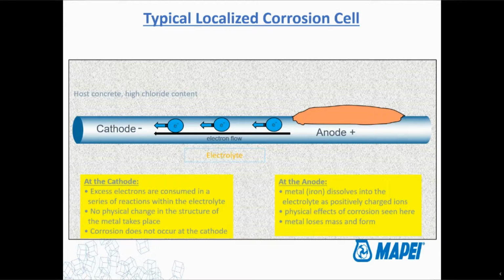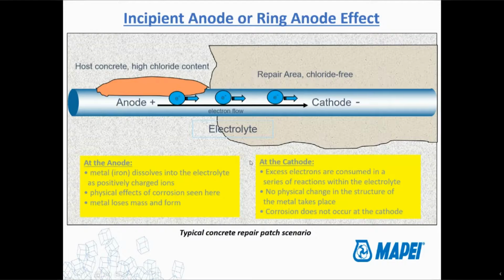It's very low potential. There's not going to be corrosion happening in that area because the steel is going to repassivate from the high pH. The low chloride concentration will also help repassivation of the steel. But you're going to have all that happening immediately adjacent to really high potential concrete on all four sides of it that does not have the protection of the passivation layer anymore, because the chloride concentration is really high. The pH has dropped. So basically, once you put that patch in there, you reverse the process.